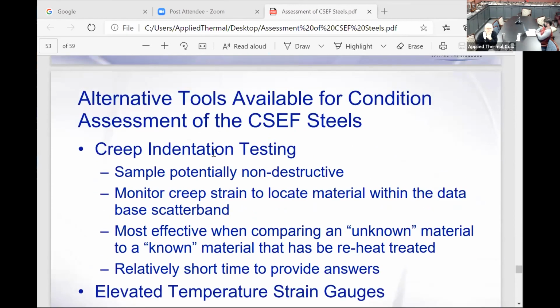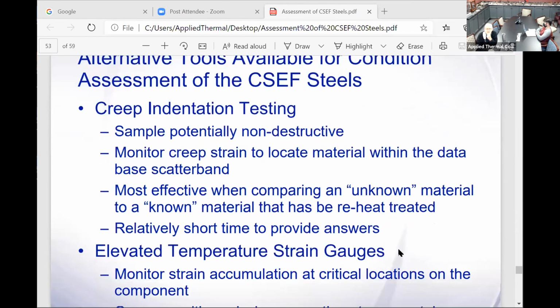And here, creep indentation testing is sample potentially non-destructive. Monitor creep strain to locate material within the database scatter band. Most effective when comparing an unknown material to a known material. And get the answer pretty quick.